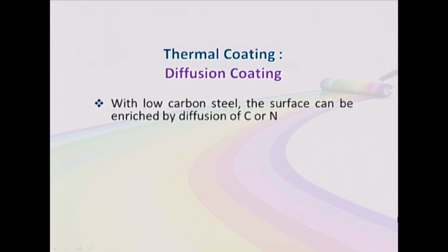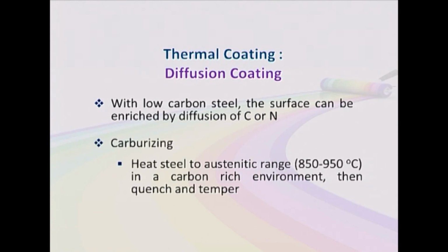Next, under the heading of thermal coating is diffusion coating. In this method, with a low carbon steel substrate, the surface can be enriched by diffusion of carbon or nitrogen. Now, diffusion of carbon, carburizing. In this method, steel is heated to the austenitic range, which is from 850 to 950 degrees Celsius, in a carbon rich environment. Then it is quenched and tempered.